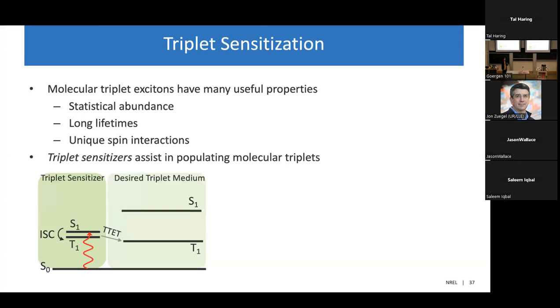For example, their statistical abundance, as the name suggests, there are 3 triplets that exist for every singlet. They tend to have long lifetimes because relaxation of a triplet excited state to a singlet ground state is spin disallowed, so it tends to happen more slowly. And then triplets are involved in some really unique spin interactions, like singlet fission and triplet-triplet annihilation, which I discussed earlier.